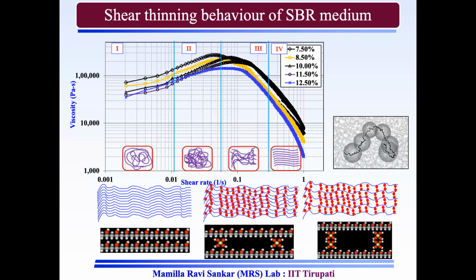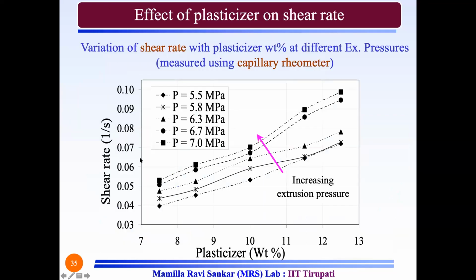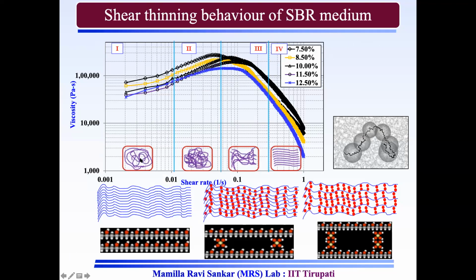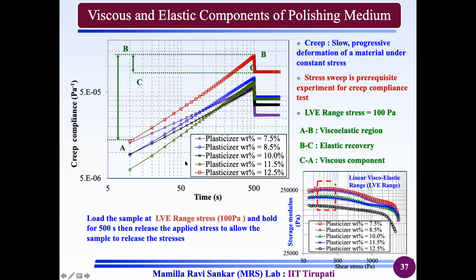Okay, as my shear rate increases, what will happen? Slowly my polymer molecular chains are climbing onto each other, making a unity and obstructing the rotation of the top plate. That means the top plate requires more torque to rotate at the specified rotational speed. So the torque is indirectly correlated, and the software will convert it into the viscosity at that shear stress. That's why, as the polymer chains climb onto each other, the viscosity will increase.